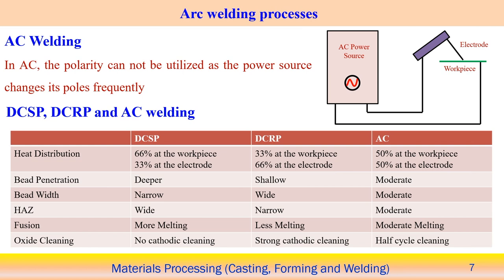So if you analyze these three different cases, DC straight polarity, DC reverse polarity and AC current welding process, we can compare the heat distribution. In case of straight polarity, the maximum heat is on the workpiece and minimum on the electrode. Similarly, in DCRP, reverse polarity, 33% heat is on the workpiece and 66% on the electrode. But if you use AC current, it is equal for both the workpiece and electrode, with 50% heat generation.